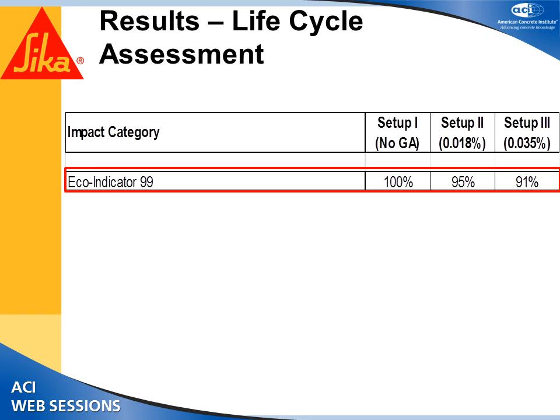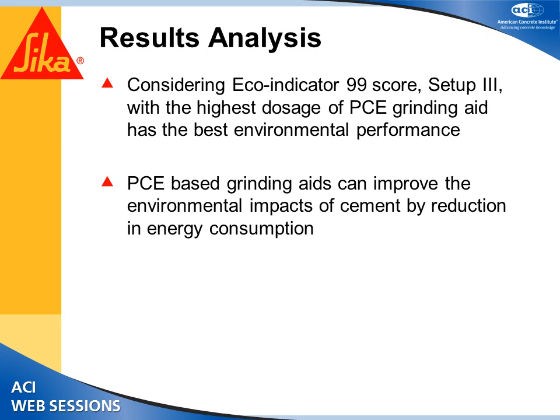For setup 1, which had no grinding aids, if that is considered as 100%, then for setup 2 the efficiency was 95%, and for setup 3 it was 91%. So what you can find out from this is that, considering Eco-indicator 99 results, setup 3, which had the highest dosage of the PCE grinding aid, has the best environmental performance. The PCE-based grinding aid can improve the environmental impact of cement by reduction in energy consumption.